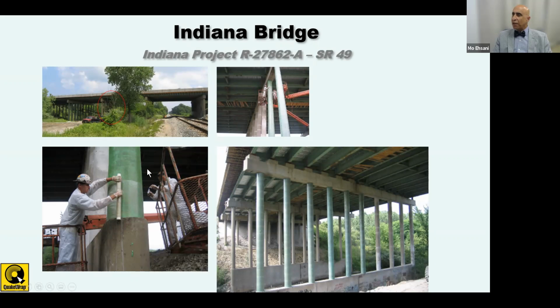This type of repair, by the way, keep in mind that when we wrap the column with this FRP, we are creating an impervious layer that will forever keep moisture and oxygen out of these columns. Because for corrosion, you need oxygen to be present, by doing this type of repair, we are going to prolong the service life of the column significantly.